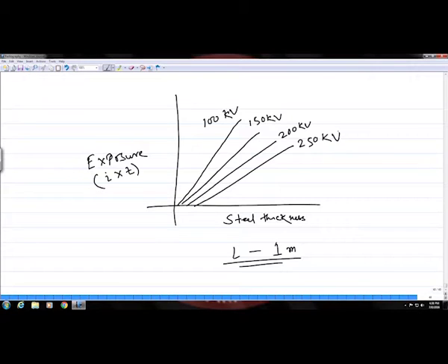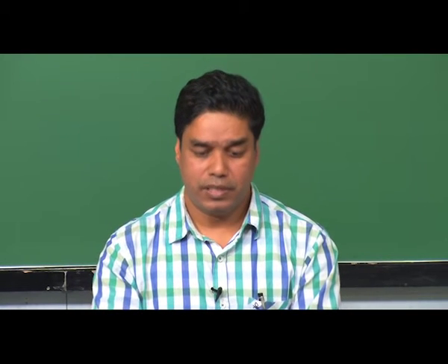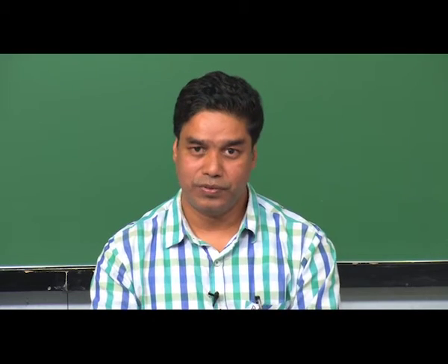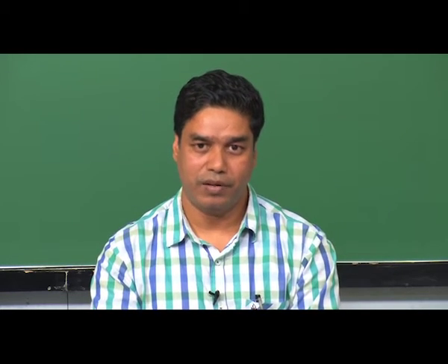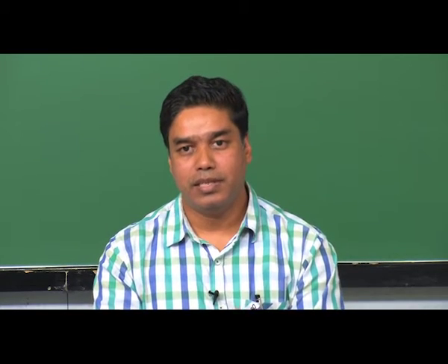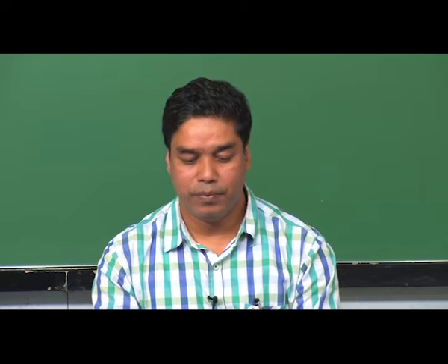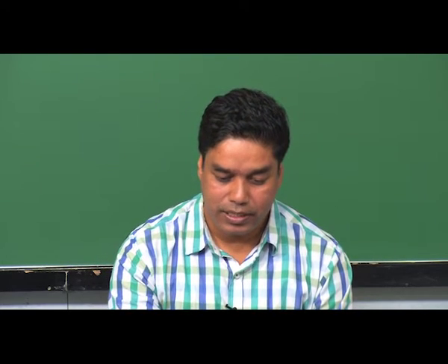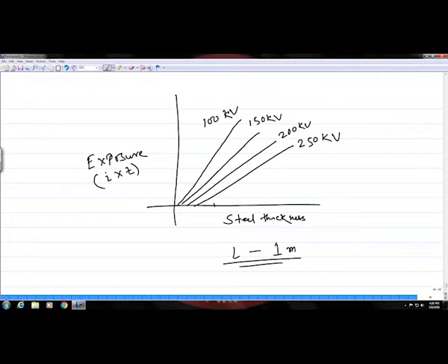So, when you do the radiographic testing, before you load the sample into the machine, you should first refer to these exposure charts which are provided by the manufacturer for that particular instrument. Then you see what is the thickness of the sample, and based upon that thickness and the tube voltage that you are using, you see what is the exposure needed.